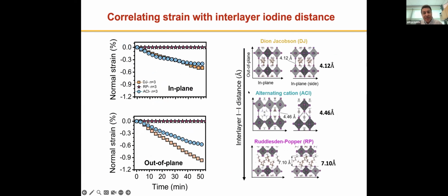Now, if we looked at all the different structures of the 2D perovskite, we found that there was a definite correlation with the interlayer iodine distance. So the apical sites here are iodide sites. What we found is that in the cases where the interlayer distance was short, for example, in the Dion-Jacobson and the alternating cation, we were able to see this effect of light-induced lattice contraction. Whereas in the case where the interlayer distance was large, like the Ruddlesden-Popper phase, we really did not see this light-induced interlayer contraction.